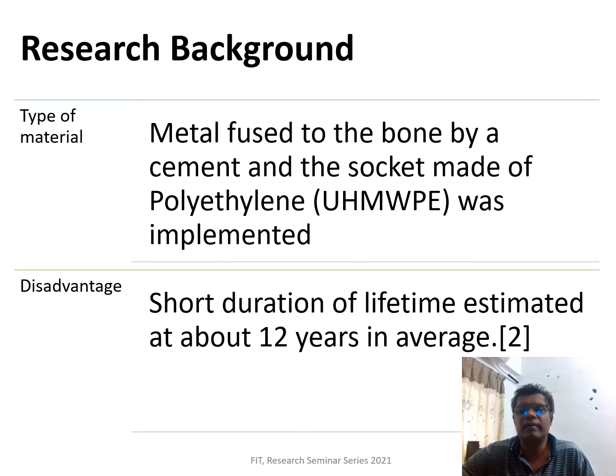At the beginning, the type of metal used to replace the hip ball was a metal fused to the bone by cement, and a socket made of polyethylene was implemented. But this technique has a major disadvantage. It has a very short lifetime. That means it's prone to failure within 12 years. So those who used this metal as a hip replacement need to replace it after 12 years. That's a big issue with this technique.